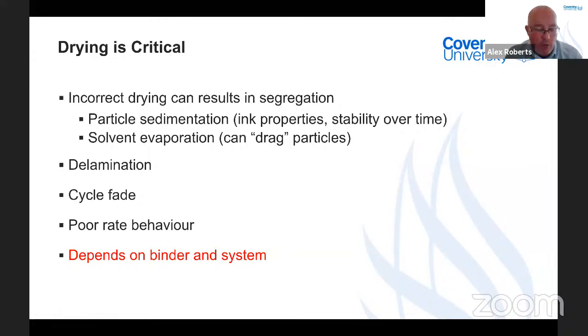If you consider how electrodes are made on a batch process with your drawdown coater, you can dry your electrodes by leaving them in the fume cupboard with NMP possibly, or on a hot plate, or you could leave them on a bench with a water-based system, or you may want to put them into an oven. But you generally give them quite a long time to dry. That's not a luxury that you can have when you go for a reel-to-reel coater. You're probably looking at less than 3 minutes is the absolute maximum you get to dry your electrodes.